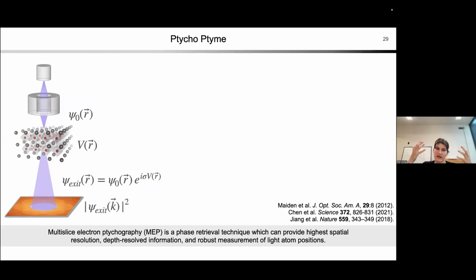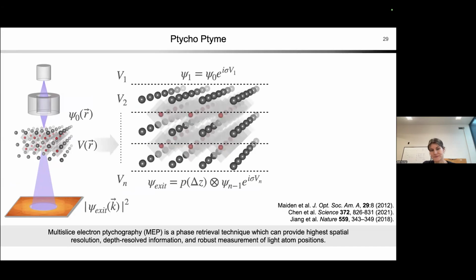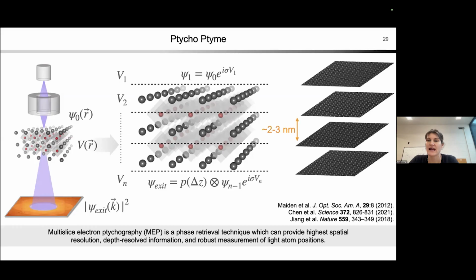And so the idea is that if we collect the exit wave function, we can actually reconstruct what potential it encountered, or what the sample was, the grating that it went through as we went through the material. Now, we need to do this for thicker materials through a multi-slice technique, which means we have to break the sample up into different vertical slices. Although this is computationally challenging, it has an experimental advantage that we've now started to regain some of that Z resolution that we tend to lose in more conventional STEM imaging.